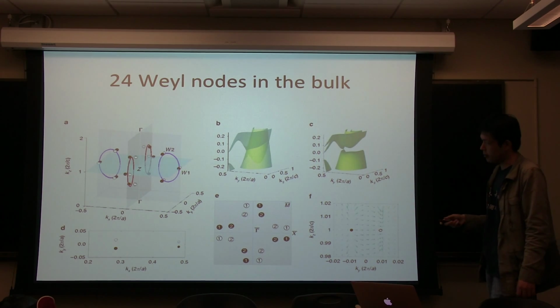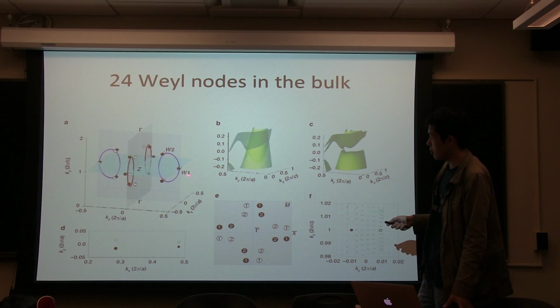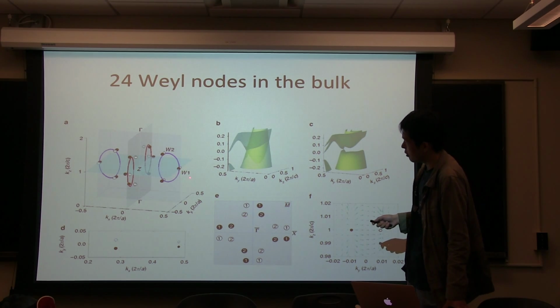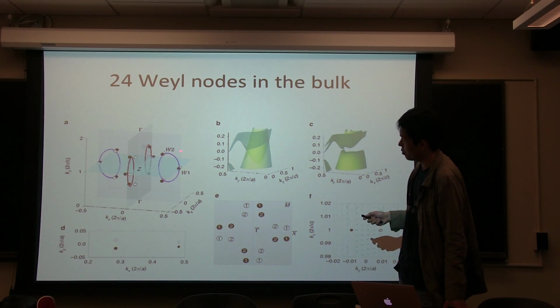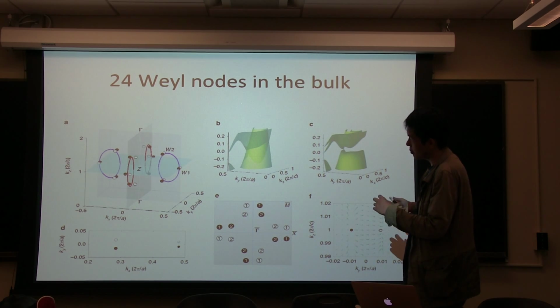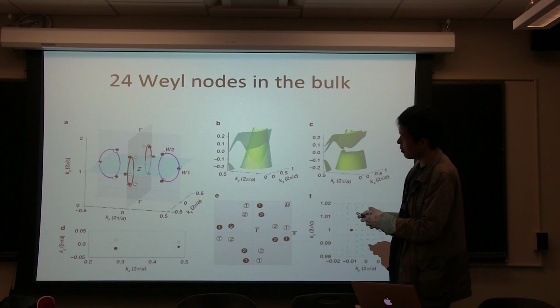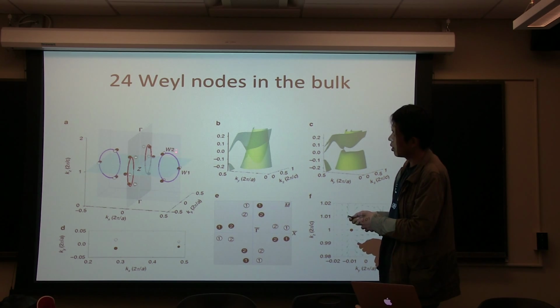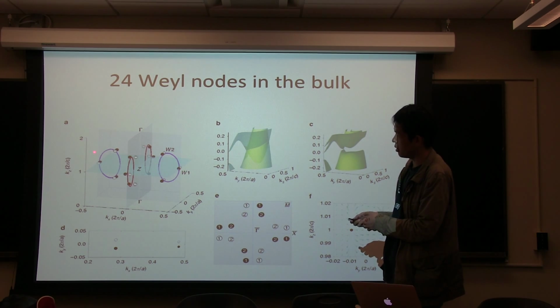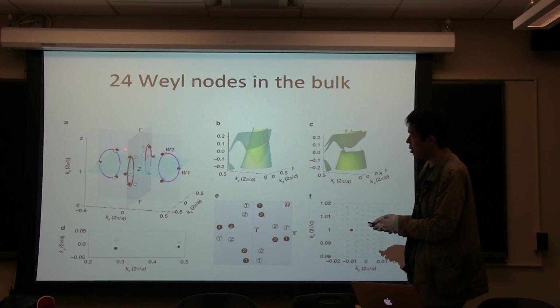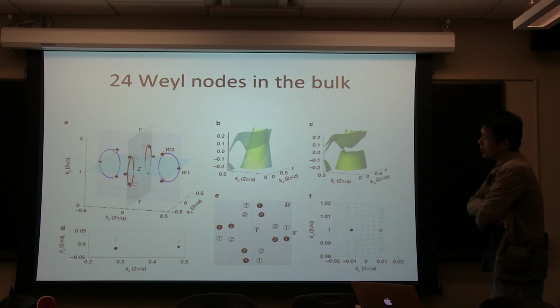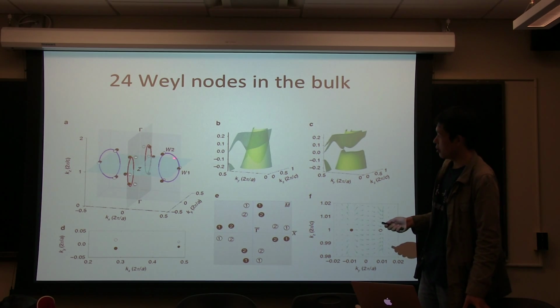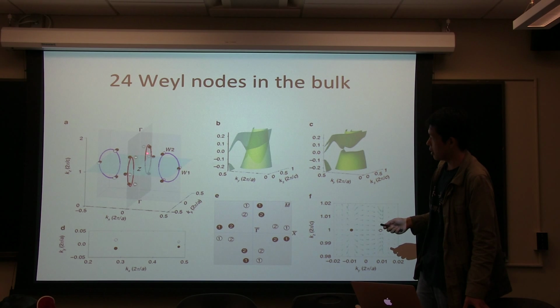Without spin-orbit coupling, as I mentioned, there's already band crossing along the high symmetry axis, and if we calculate the full BZ, we find that without spin-orbit coupling, the band crossings are actually one-dimensional. That means the conduction band and valence band dip into each other, and they form this one-dimensional, ring-like touching. In the first BZ, there are 4 of them. They're on the kx equals 0 and ky equals 0 mirror planes. And when I add the spin-orbit coupling, the nodal lines themselves are gapped out.